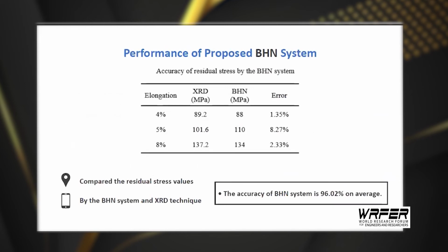After obtaining a prediction equation, the BHN system was used to measure the residual stress again. This is compared with the residual stress obtained by the XRD technique to test the performance of the BHN system. Therefore, the average error of the BHN system is 3.98%. The system has a measurement accuracy of 96.02% on average.